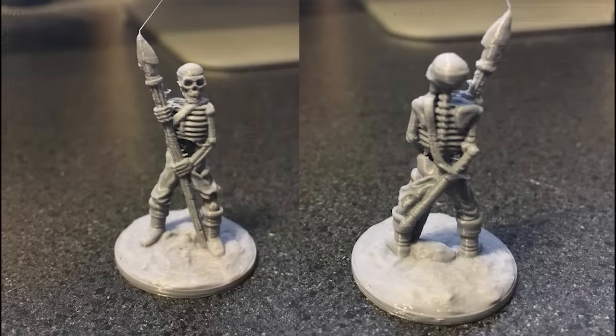One of the things that I see most as far as a problem with using this setting is the under extrusion it creates. If you look at this photo, there are definite bands of under extrusion on the skull and all throughout the length of the spear shaft and even down on the rear of the right boot in the rear photo there. Other things I notice is increased banding from the individual layers. Areas like the sword scabbard in the rear view that were visually perfectly smooth with a standard consistent 0.1 layer height, now there is definite banding.